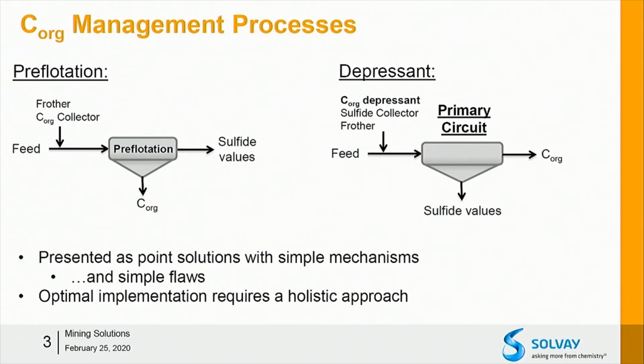You know, you could run a pre-flotation circuit with a frother only, generate a carbon concentrate. Your sulfide values are then in the pre-float tails, and they can proceed to the primary circuit where you can float them in a standard way. Or you can use a depressant in your primary circuit, where you're adding an organic reagent to make the carbon hydrophilic so it does not float, alongside your sulfide collectors, generate a sulfide value mineral concentrate, and then your carbon reports to the tails. And so these are presented in a straightforward way, and they seem to have very simple flaws from a conventional view.